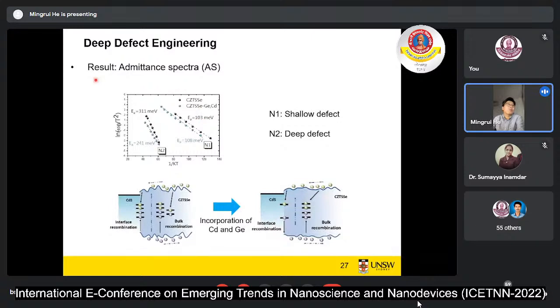Here I would like to go directly to the deep defect engineering. Similarly, I did the admittance spectroscopy here to characterize what kind of defects we had in our materials. From the data we can get two different defect levels: one is a shallow level defect, N1, and another is a deep level defect, N2. The shallow level here should be related to the copper zinc anti-site defects, as I mentioned before. Another one, the deep defect, we don't know, but it should be related to some tin related deep defects.